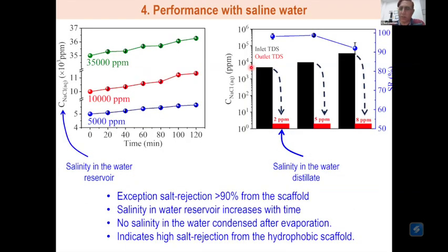But we have done a lot of different tests to prove that the salinity is actually rejected. What happens is, water vapor evaporates and the salt is all left behind. Because the salt is left behind on a well-defined membrane, we can now take the membrane, clean it, and put it back for use. So every day you take the membrane out, clean it, and put it back, and you are good to go. And this can be done in the evening when the sunlight is not available.